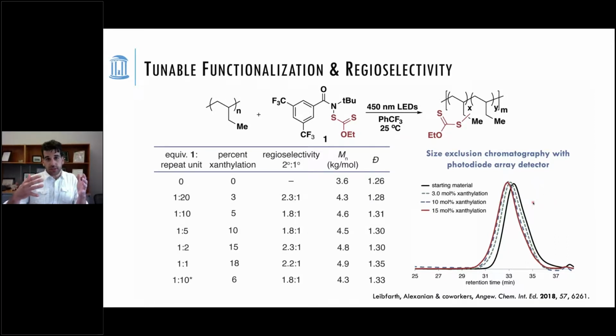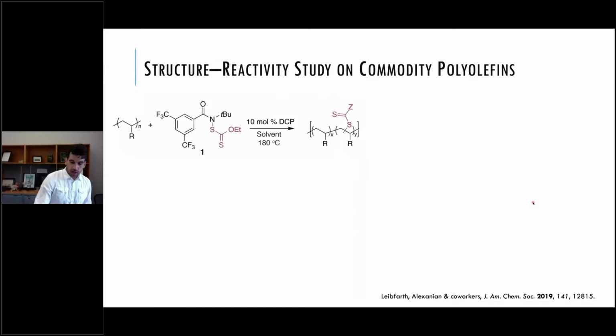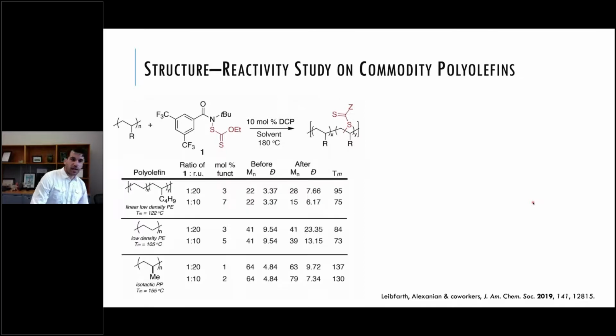And that's a really big deal because this is one of the first technologies that uses this radical chemistry to functionalize something like polypropylene that doesn't degrade the polymer. So that means the properties of this polymer will still be just as good, but now it'll have this additional functional group on it. We then went on to do this chemistry on commercially relevant polymers.